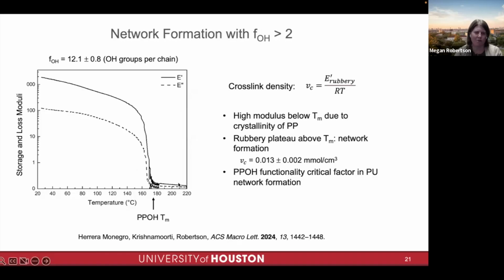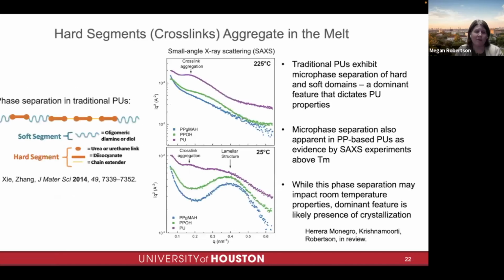And from this plateau modulus, which would be this E prime rubbery, we can calculate the cross-link density. So in this particular material, we had about 0.01 millimoles of crosslinks per centimeter cubed of material. But essentially, this is telling us we indeed formed a network, which was our goal. We want to make a thermoset polyurethane.